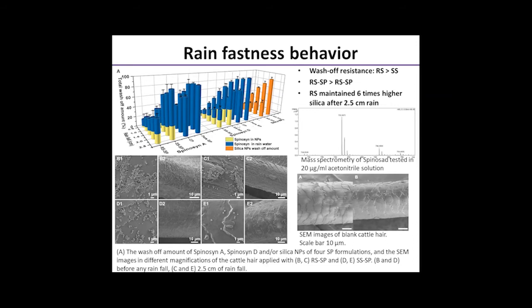The wash-off active ingredients were measured and divided into 2 parts: the spinosyn in rainwater and the spinosyn in silica nanoparticles, which are shown in blue and yellow bars respectively. Under 2.5 centimeter artificial rainfall, the calculated spinosad A residue maintained on the cattle hide for rough spinosad is 5 times that of the smooth spinosad, 2 times more than the benchmark commercial product, and over 7 times more than pure spinosad. The spinosad D residue content calculated on the cattle hair shows a similar trend.